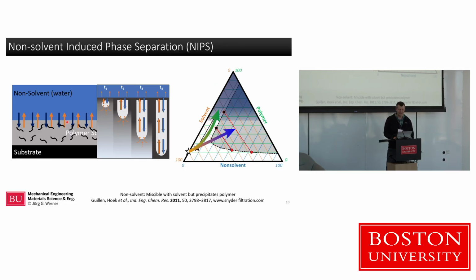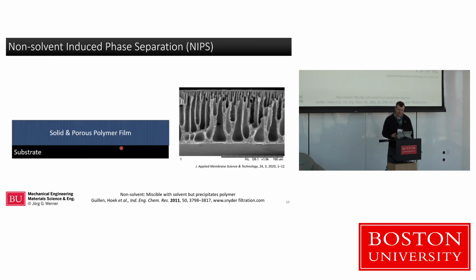Now that all happens at the interface between the 2 liquids, and it grows away from these interfaces. That's how we get these high aspect ratio pores in a very simple process. We literally just paint and dunk, and the rest is happening by soft matter phase behavior that we try to control, but we don't have to individually write it. And you end up with these films. It's really straightforward. It's done roll to roll on an industrial scale for filtration membranes.